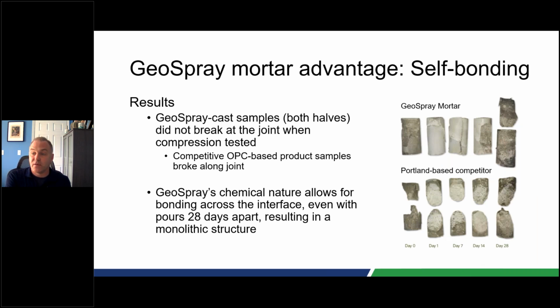28-day cure. And you'll see in the pictures here, the ones on the top are from the Geospray samples. The ones on the bottom are from a standard Portland-based mortar that's available in this marketplace. You can see the joints pretty clearly in the Geospray samples because the color variation of the samples is not always the same. We don't quality control for color, so you can see a little variation from day to day. But you can see that the joints are not where it's breaking, which means they're as strong as the rest of the material. And that's a benefit specifically because in almost every case, you are applying multiple layers together. This is really due to the specific chemical nature of this product.